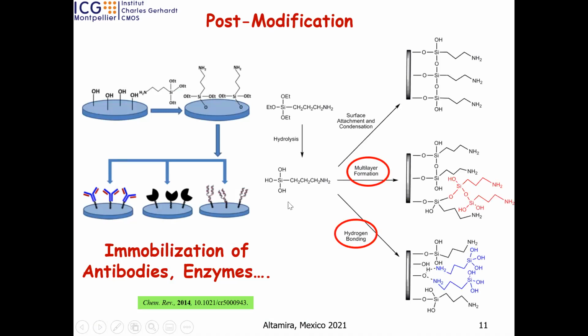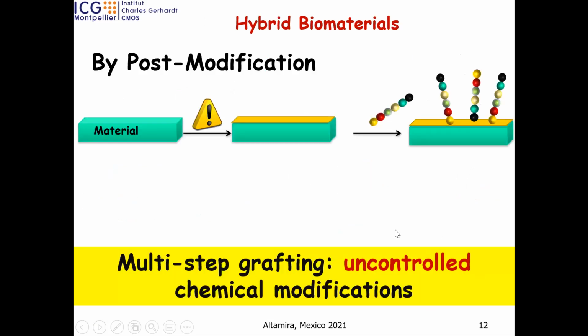But the problem, if you can see, here you have the good one. They explain that a major time you have multi-layer, so you can't control the immobilization of amino group. So sometimes you have something like this, and sometimes if you take aminopropyl triethoxysilane, you have adsorption of amino group on the surface, and then you don't have only an NH2 on the surface. You have some alkoxy group, hydroxy group. So it's not very well controlled.